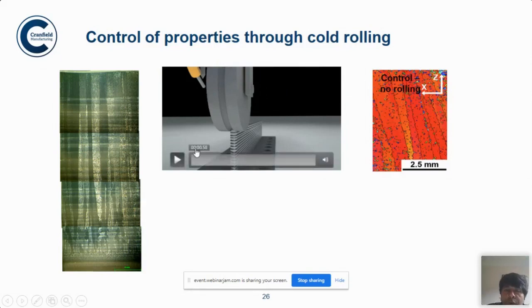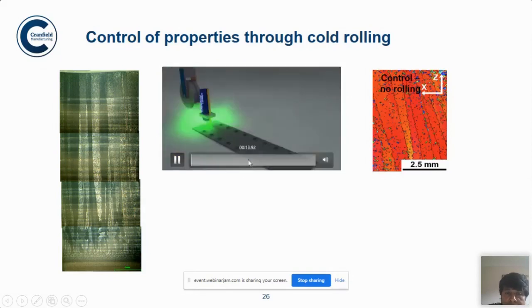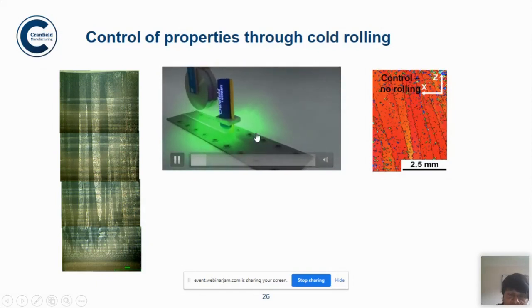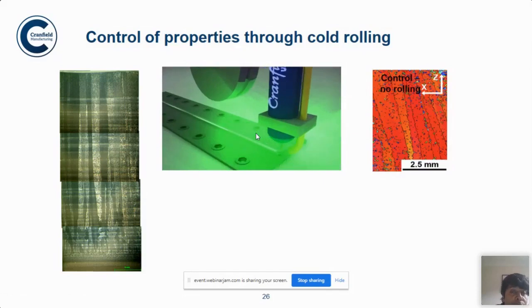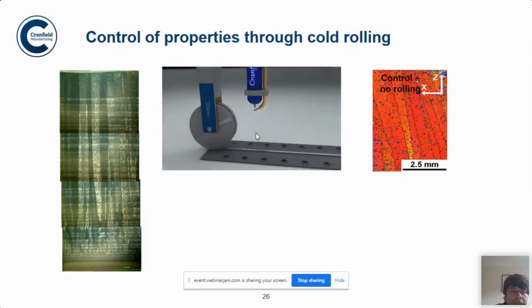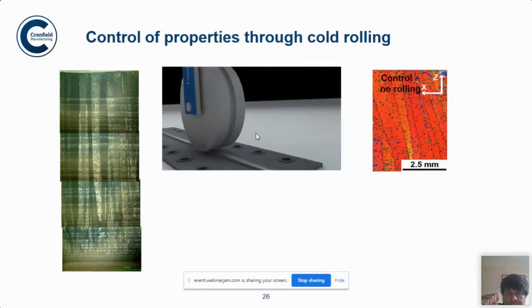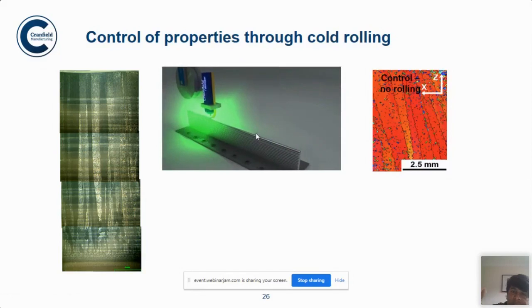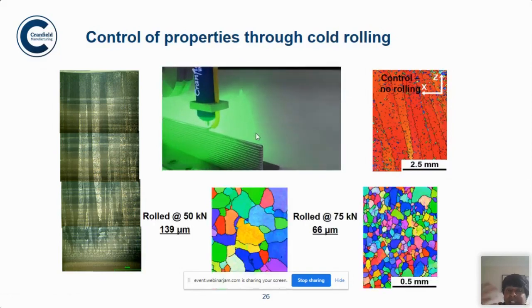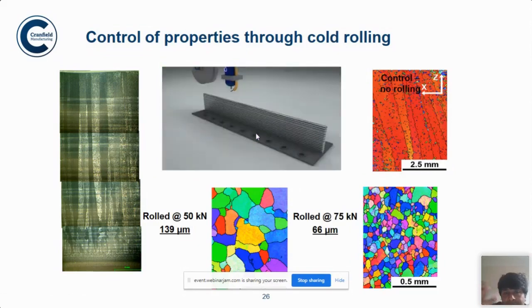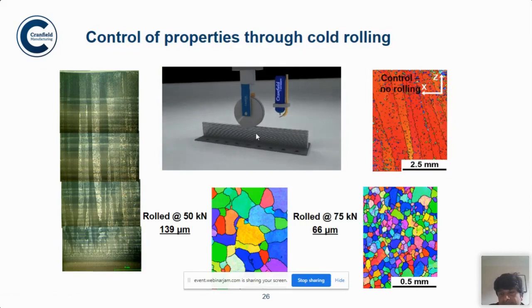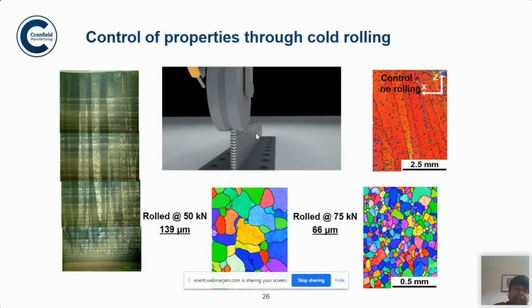Now we invented a process of cold rolling, by which when we deposit, we can roll a layer, and doing that, while rolling the layer, you induce cold straining in it. The rolling of the layer is done at a temperature lower than the recrystallization temperature of this alloy. So you deposit a pass, wait for some time, and do this rolling, and you induce cold straining. So when you deposit the next pass, what will happen? You're going to redistribute the strain. So basically, you're not creating a recrystallized structure, or you may create a recrystallized structure, but you are obviously creating high angle grain boundaries as compared to the columnar dendritic grains.